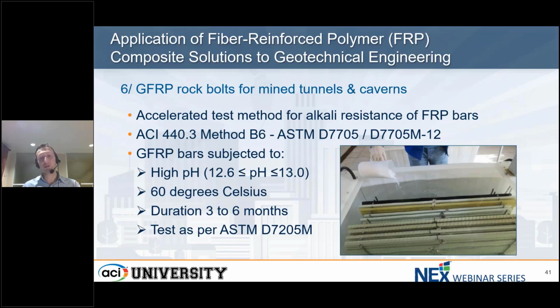And of course, that's because we know already very well that GFRP is resistant to corrosion, or actually there is no corrosion as such with GFRP. The concept of having rust or the material physically changing doesn't exist. There's no change of mass, no change of weight. However, as it's well documented, GFRP will be affected by high pH, the same way when you have moist concrete, you have a high pH, and this alkalinity will reduce the bar performance. The vast majority of geotechnical anchors are, of course, using cement grout. And for this reason, we are facing the same condition.